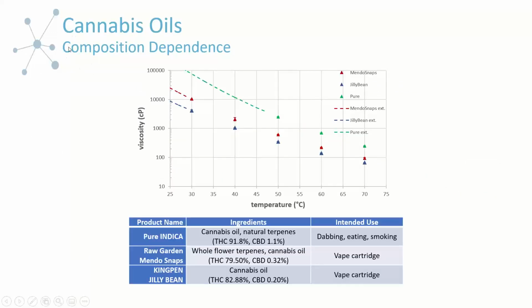The last point I wanted to make about these is just to emphasize the composition dependence. These were just some commercial products that we purchased, and we can see some of the ingredients in these products, where there are seemingly modest changes in composition, whether it's the THC or the CBD content of these. And the composition seems to vary depending on the specific intended use. But you can see that even with these modest changes in composition, we can see nearly an order of magnitude difference in the viscosity. Again, viscosity is a function of temperature. And in this instance, we did use the model fit to extrapolate back down to cooler temperatures, since this was measured in our automated system, and getting down to these low temperatures, extremely high viscosities wasn't really possible. So they're quite dependent on composition. Seemingly similar products will have quite different behavior.